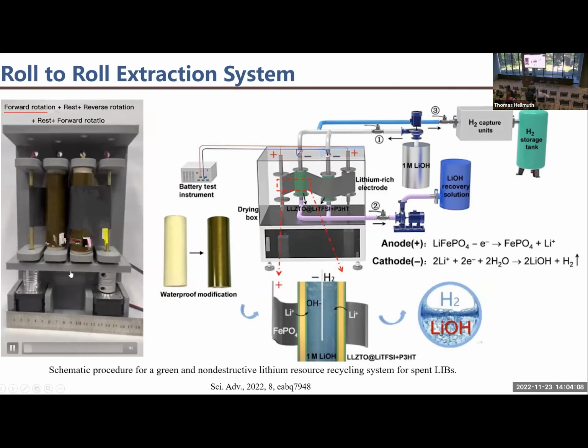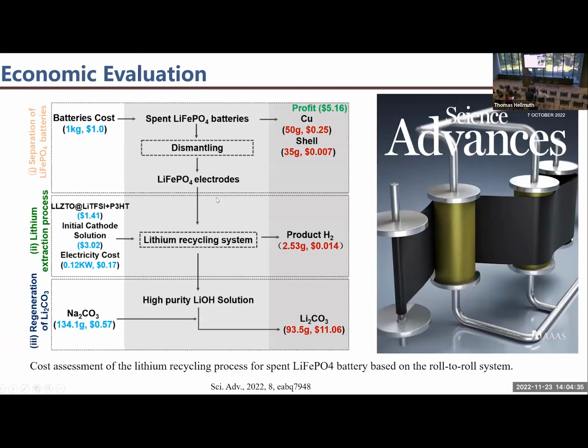I don't know if the video is fine or not, but this is a very attractive method because we don't need any pretreatment. We don't need any high temperature, any decomposition. So basically the electrode surface is maintained so we can extract other metals later. But at the moment, we can directly get lithium. We don't need to do anything. We simply pass our electrodes through these columns, and then we can get the lithium. So that's the idea from this paper.